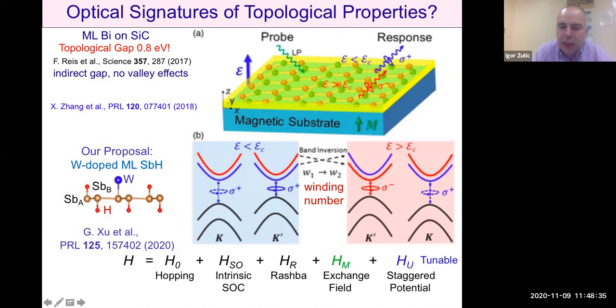But what is basically important is to make the effect valley selective. So we are trying not to just do the same thing to both valleys, but isolate one of them. And so what is shown here is that in the K prime valley, we are able to realize band inversion. So this is then a combination of this staggered potential and exchange field, if this helps.